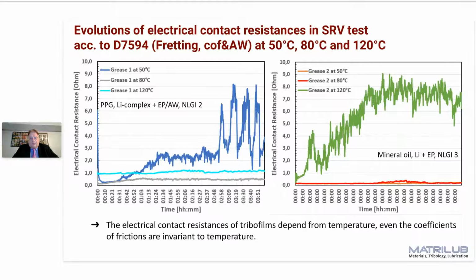The crucial point with the electrical contact resistance or the electrical properties is shown here. You see two greases which are high performance greases. And now you make a fretting test according to D7594 at 50, 80, 120 centigrade. And you see here the electrical contact resistance, not the friction signal. On the left side at 50 centigrade, you have a quite high electrical contact resistance, which at 80 and especially at 120 centigrade is very low. The other grease has at 50 and 80 centigrade a low contact resistance, but at 120, the contact resistance is high.